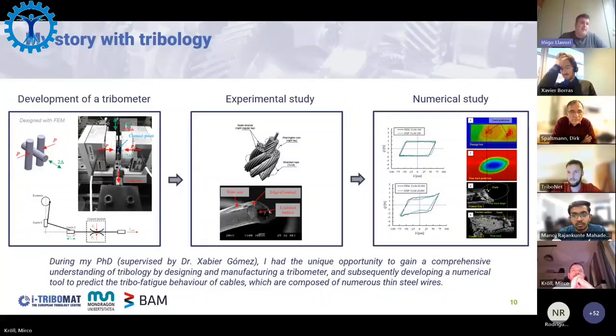So in this sense, I used the finite element method to design the tribometer, and then I also used the numerical study to correlate what was happening during the tests. On the right-hand side, you can see some friction loops, and I was able to correlate very well how the friction loop changed during the test. I had first a kind of flat-topped friction loop, but then this non-Coulomb behavior appeared, which you can see in the hook-like shape at the end of the stroke.